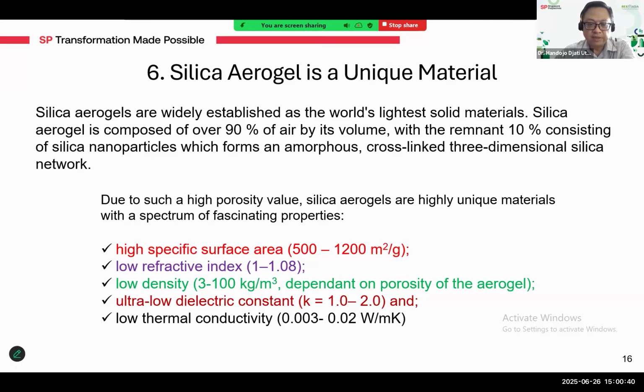With this, the density can go up to a maximum of only 100 kilograms per cubic meter, so it will more likely float in water. This also depends on the porosity of the aerogel. We have an ultra low dielectric constant of 1 to 2 and low thermal conductivity, maybe up to 0.02 watts per meter kelvin.